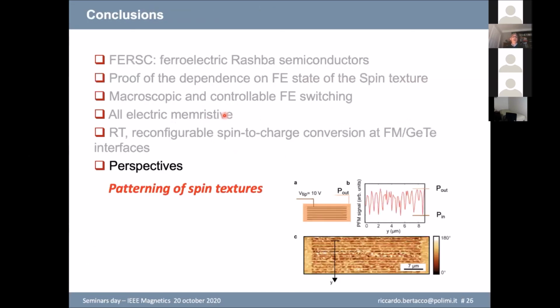And that's all. I have been very glad to give this seminar to show the advance of our research, which means that nowadays we are in a condition to say that we have the possibility to control the ferroelectric states of germanium telluride and also spin to charge conversion effects at the ferromagnet germanium telluride interface. And what's the perspective of this work? Obviously, to try to use the possibility to pattern spin texture by, for instance, writing different ferroelectric textures in our materials, to perform experiments on more advanced devices, playing with spin texture patterning in our devices. So that's all for your attention, and I'm ready for questions if there are any.